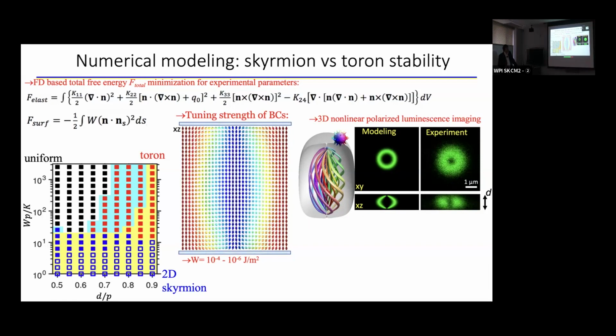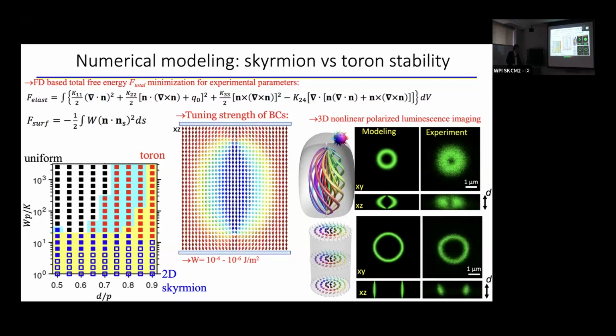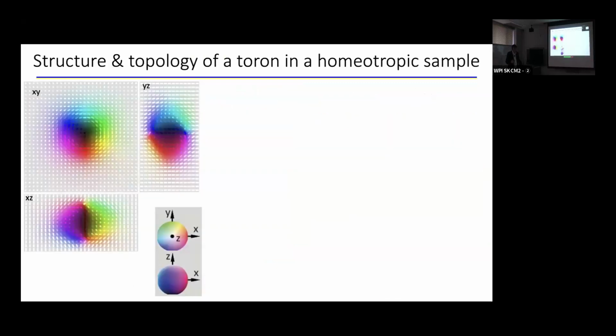And now, as we can see, we can image these topological solitons with the help of nonlinear optical imaging, which is based on 3-photon absorption of the molecules of liquid crystals themselves that then emit as we excite them in infrared, emit visible light because of a third-order nonlinear optical process of absorption and then subsequent emission. And then as we obtain different cross-sections in the plane perpendicular to the far-field director and containing the far-field director, we can see good agreement between the experiments and these simulated results. And also we can find conditions under which skyrmions are stable too. And actually both can be utilized to control topography in different ways.